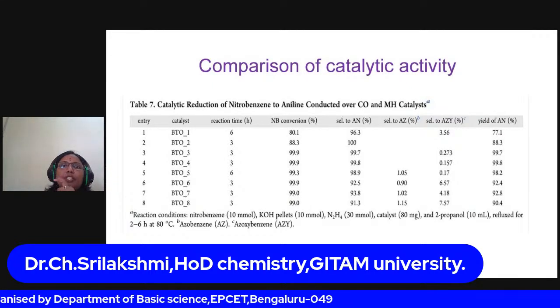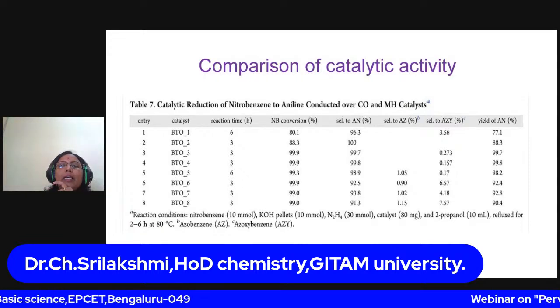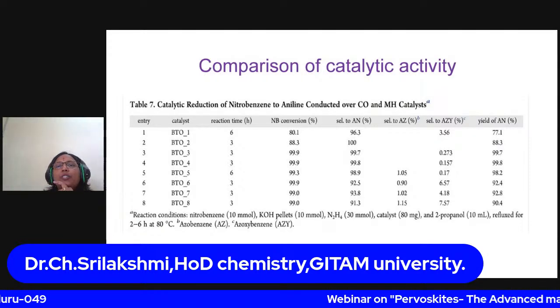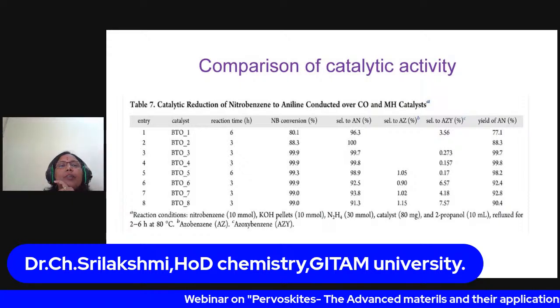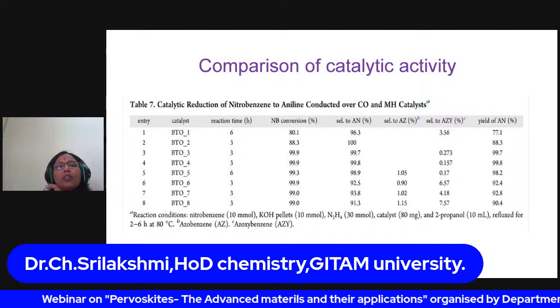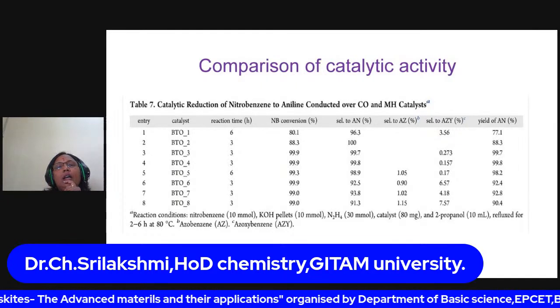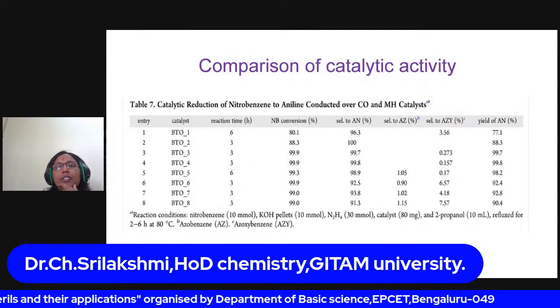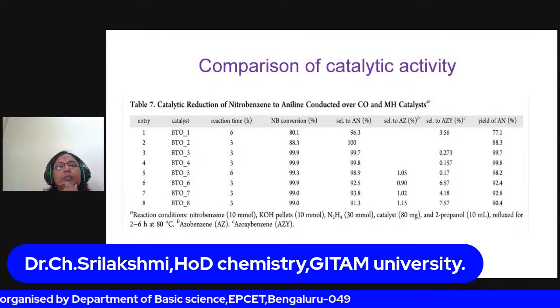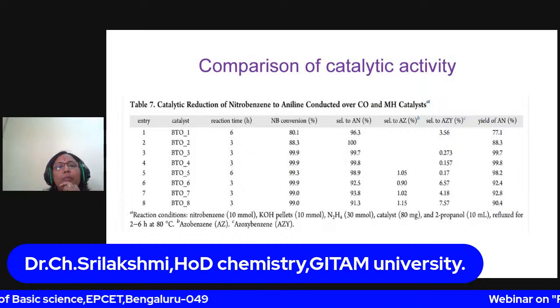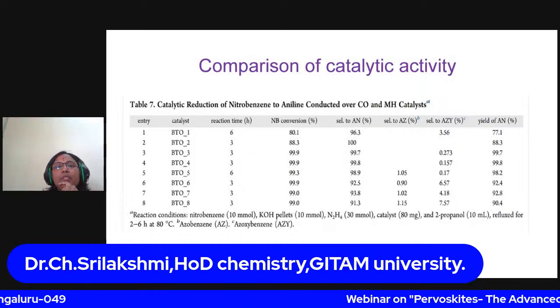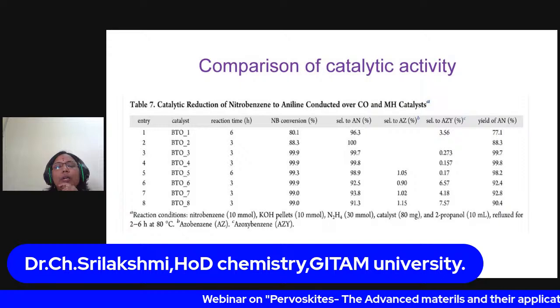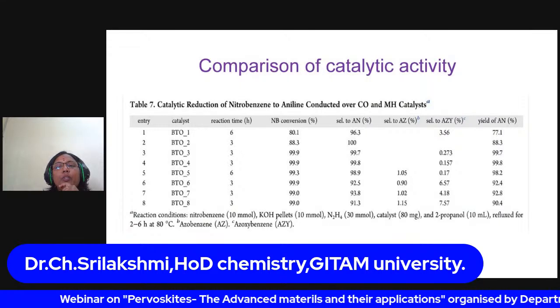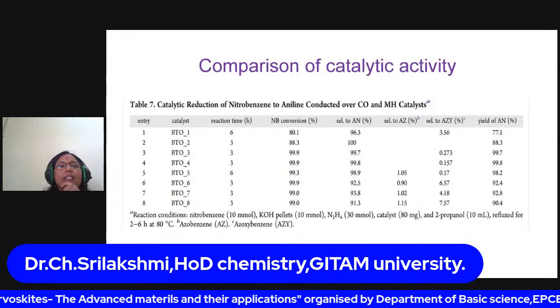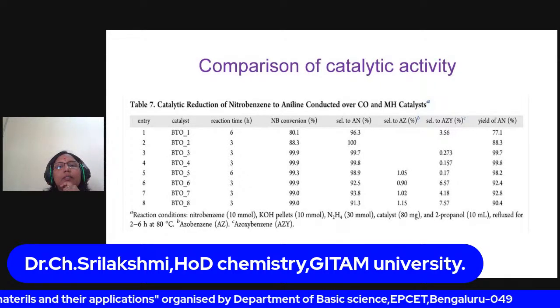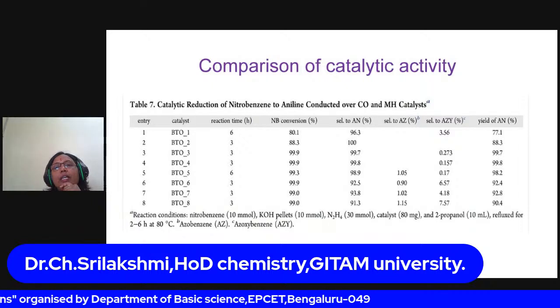It facilitates the reaction in a short time here also, but in the conventional case, in terms of activity it clearly improves the conversion as well as the selectivity. With microwave synthesis, everything is constant and it only facilitates the reaction in a short time. These are the conditions we used: the reaction is conducted in a round bottom flask by dispersing 80 mg catalyst in a nitrobenzene, KOH, and hydrazine hydrate mixture, with 2-propanol as solvent, refluxed 2 to 6 hours at 80 degrees C. All the products are analyzed using GC-MS.